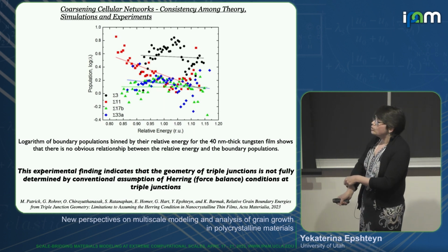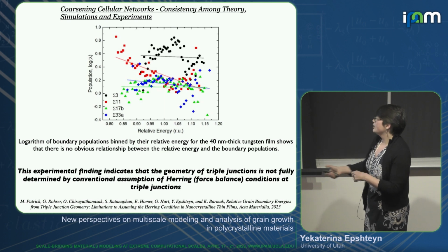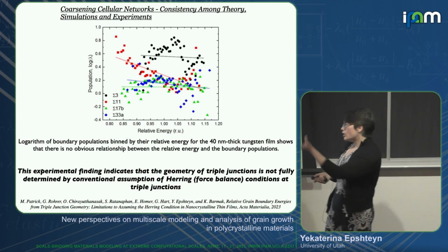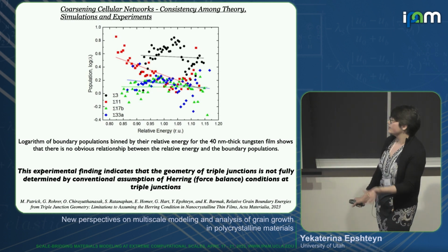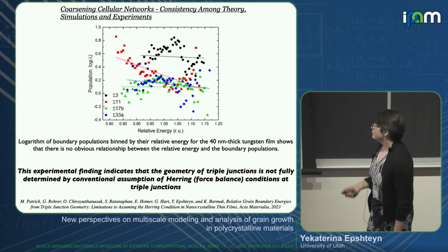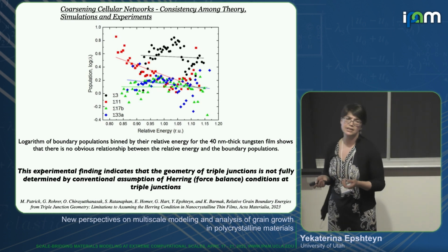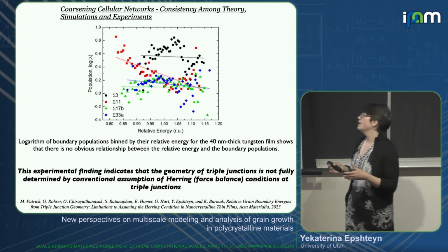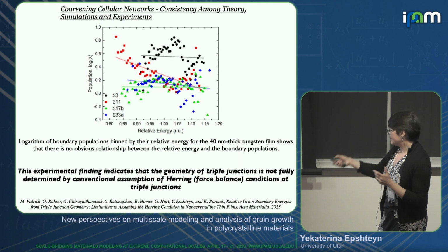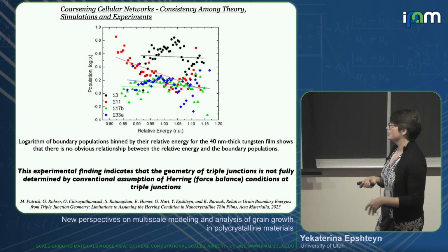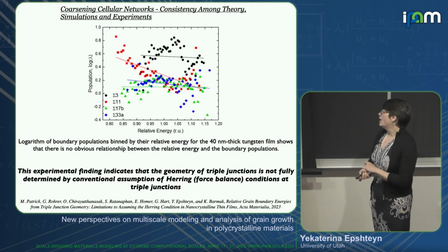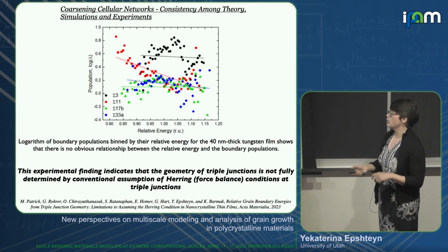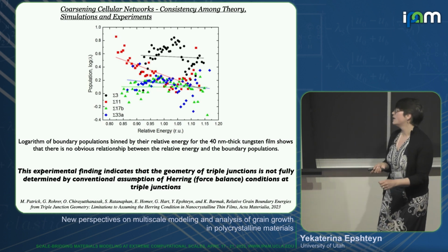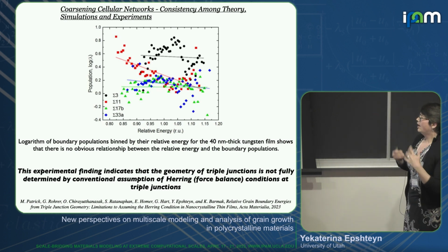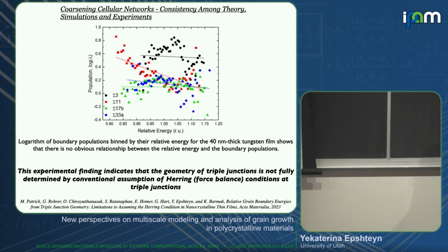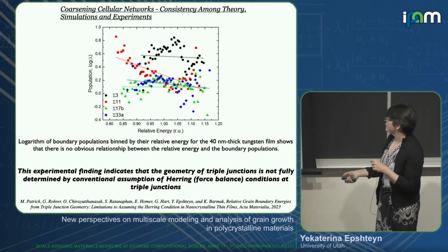conditions at triple junction, we did not observe any inverse relations between grain boundary energy and boundary population, which not directly, but indirectly indicates, and that was for the first time, that the geometry of triple junction is actually not fully determined by force balance conditions. I don't know if it's because maybe you have to consider other forces at triple junctions. You maybe need to assume drag or finite mobility of triple junctions, but it's consistent with our mathematical and computational model, and our goal now is to try to check that directly, to try to obtain more direct data of what happens at the triple junctions.